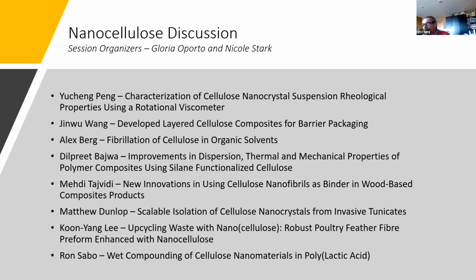Based on this, and also having in mind that we want to upscale the technology, we studied the fibrillation of eucalyptus kraft pulp at pilot plant scale by means of a 12-inch refiner and a homogenizer, in water as well as in concentrated acetic acid. Our results are practically four. On the one side, the fibrillation of nanocellulose is possible in water as well as in an organic solvent, in our case acetic acid. But a little more energy is needed if an organic solvent is used.